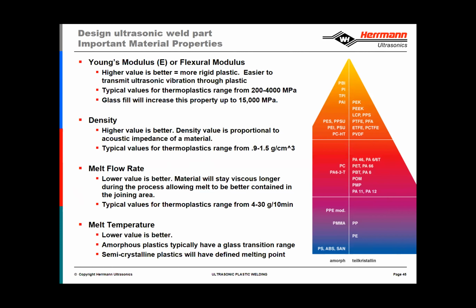And then finally, melt temperature. The lower the value, the better, which typically means lower amplitude requirements. So heat and amplitude are analogous terms, so we will sometimes use those interchangeably. So having a lower melt temperature means that amplitude requirements are typically lower as well. And just another point about melt flow index and melt temperature, when we look at compatibility of materials, these are the two numbers that we look at, the melt flow index and the melt temperature.